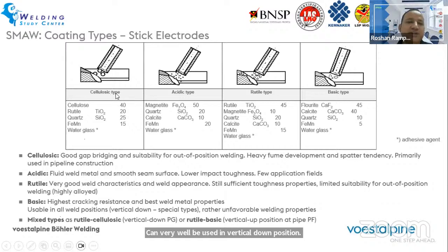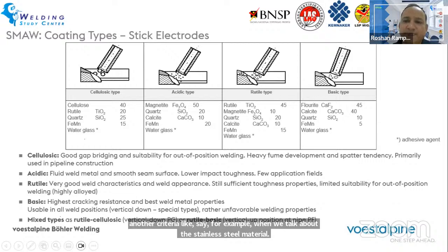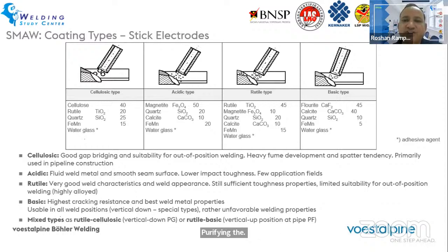And why do we need vertical down position? Because the welding productivity or the speed of welding is more when we do in vertical down position. But there are certain improved versions of basic type which are also designed for vertical downward position welding. Then another criteria, say for example, when we talk about the stainless steel material used for cryogenic applications, the basic type has a property of purifying the molten metal to a greater extent so that we can achieve higher impact properties at lower temperature up to minus 196 degrees Celsius.